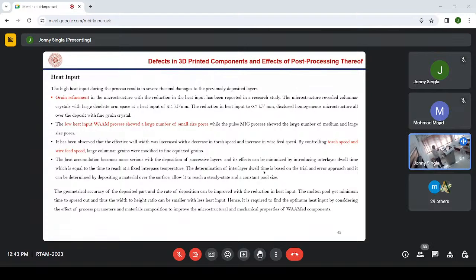Heat input. High heat input during the process results in severe thermal damage to the previously deposited layers. Grain refinement. This is one of the challenges in the microstructure, with the reduction in the heat input reported in a research study. The microstructure revealed columnar crystals with large dendrite arm spacing at a heat input of 2.1 kJ per mm. The reduction in heat input to 0.7 disclosed a homogeneous microstructure all over the deposit with fine grain crystals. That means heat input should be on the lower side if you want to have a better microstructure.